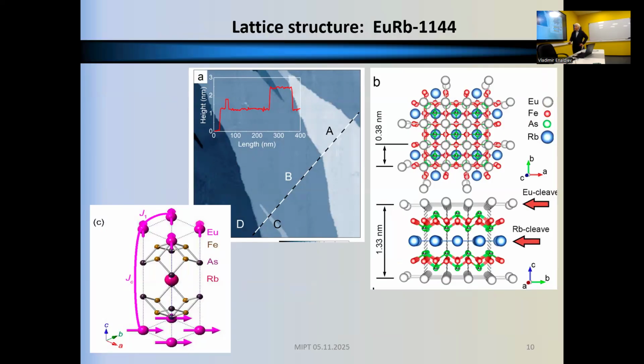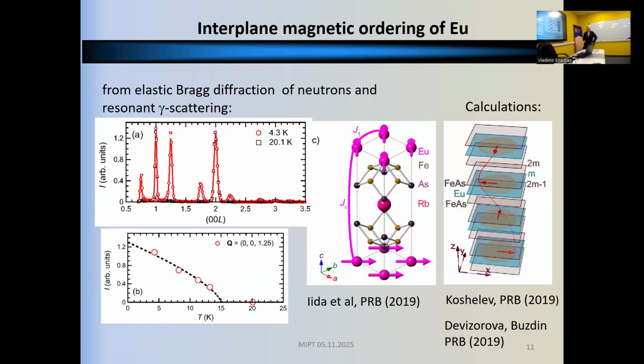So again, this picture illustrates what I said. The largest exchange is in plane, and then the antiferromagnetic exchange interaction between various planes, and I will then tell how it is done. And theoretically it was predicted, calculated, and experimentally confirmed that the magnetic polarization rotates by pi/2 from layer to layer. This was an experimental outcome from elastic scattering by polarized neutrons, and beyond the regular peaks located at the expected distance, there are some satellites which die at the temperature of magnetic ordering.